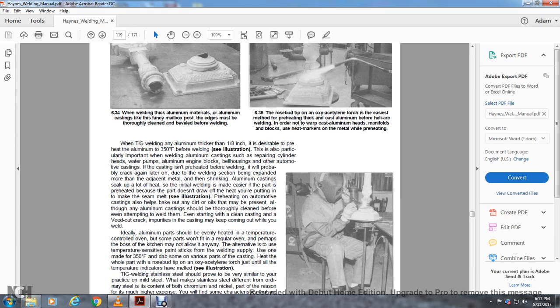because the welded section may expand more than the adjacent metal, then shrink. An aluminum casting soaks up a lot of heat. The initial welding is made easier if the part is preheated, because the part doesn't draw off the heat while you're putting the filler in the seam of the melt. Preheating the automotive casting also helps to bake out any dirt and oil that may be present with it. Although aluminum castings should be thoroughly cleaned before even attempting to weld.